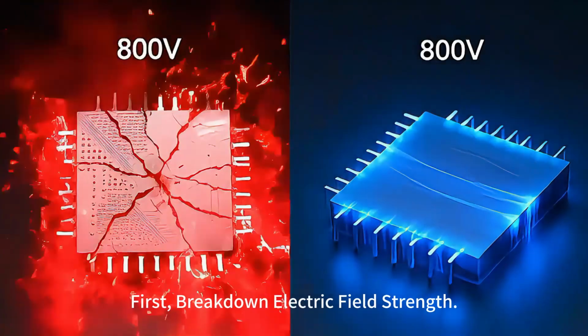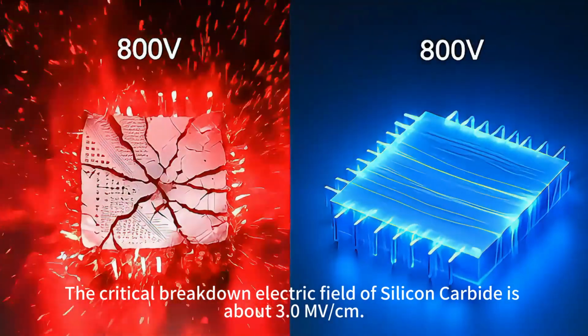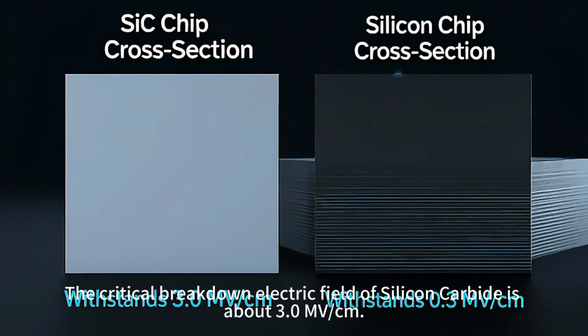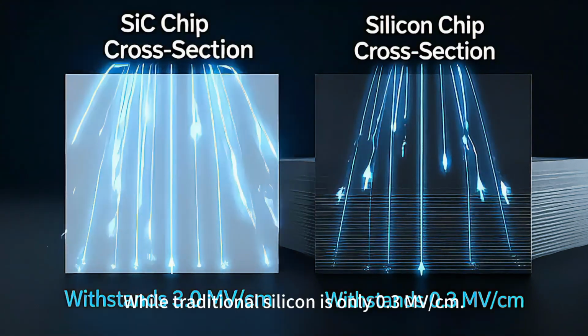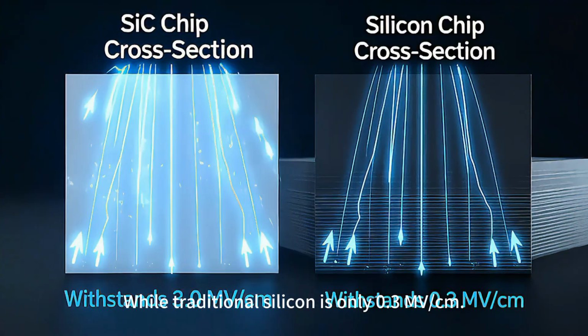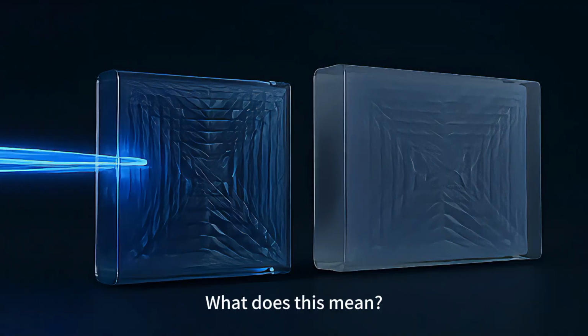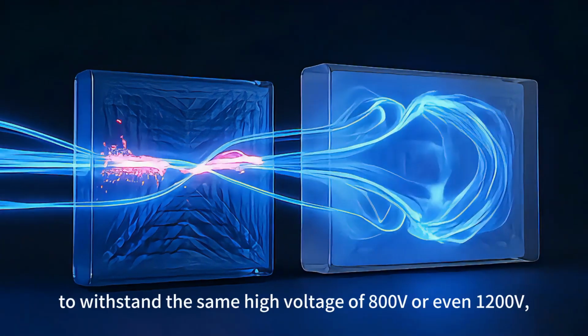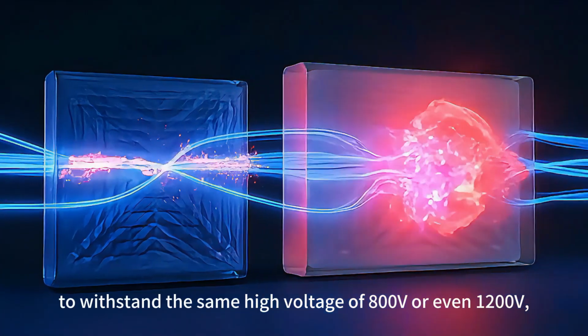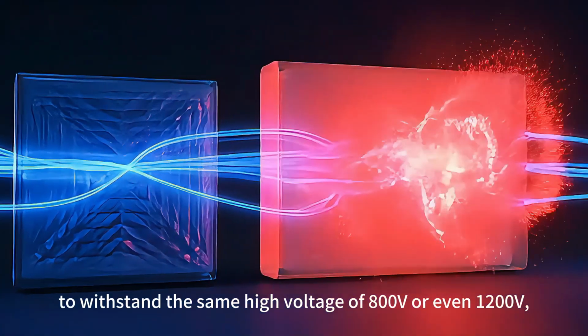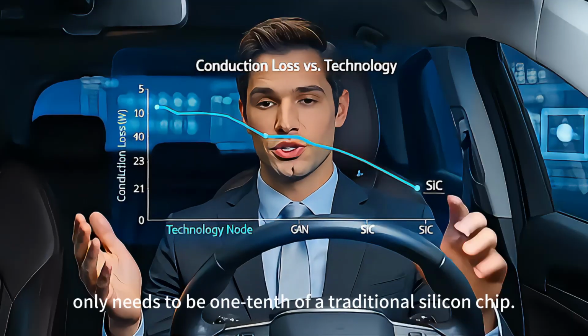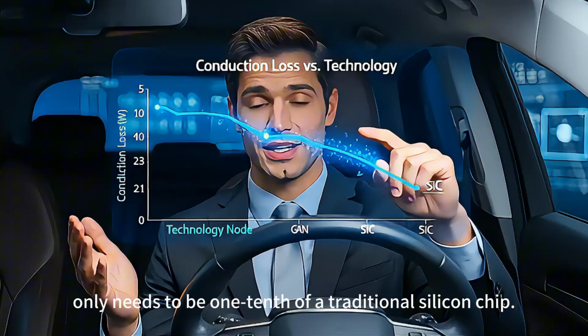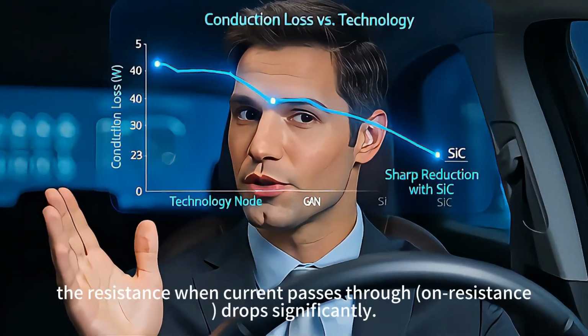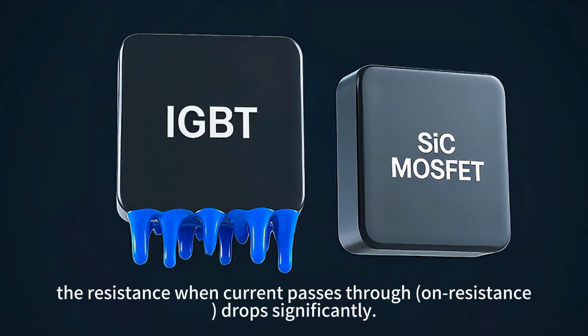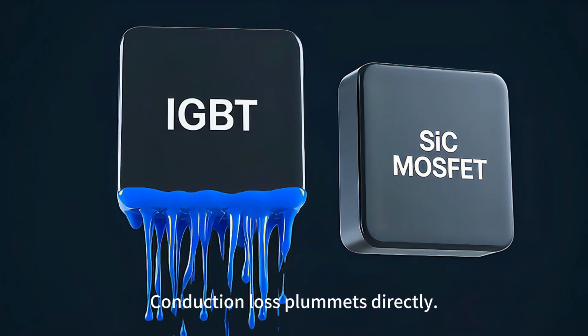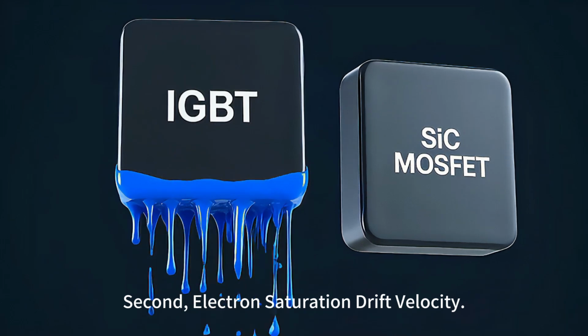First, break down electric field strength. The critical breakdown electric field of silicon carbide is about 3.0 megavolts per centimeter, while traditional silicon is only 0.3 megavolts per centimeter, a full 10 times difference. What does this mean? This means to withstand the same high voltage of 800 volts or even 1,200 volts, the thickness of a silicon carbide chip only needs to be 1/10 of a traditional silicon chip. With a thinner chip, the resistance when current passes through, on-resistance, drops significantly. Conduction loss plummets directly.